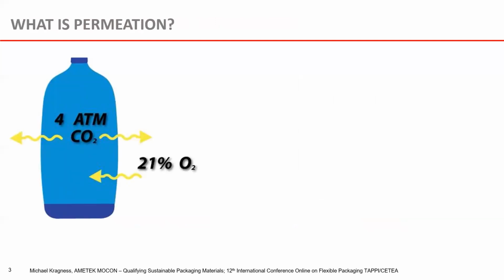So we see here we have a 2-liter bottle, and it's highly pressurized with carbon dioxide gas. And then on the outside in the atmosphere, we have 21% oxygen. Now, at first glance, you may be thinking, well, how can oxygen that's at 1 atm permeate into a bottle that's at 4 atm of CO2? And the reason why is because of partial pressure. Now, partial pressure is really the driving force of permeation. So a general rule of permeation is more of it will go to where there is less of it, because it always wants to reach an equilibrium.